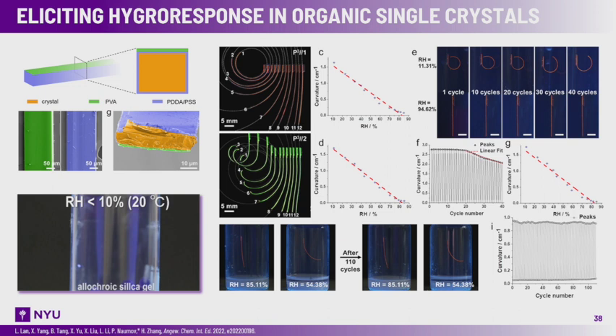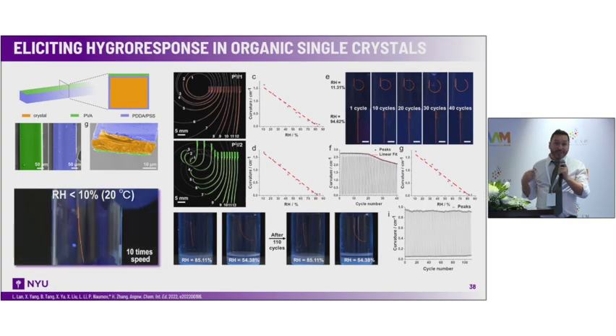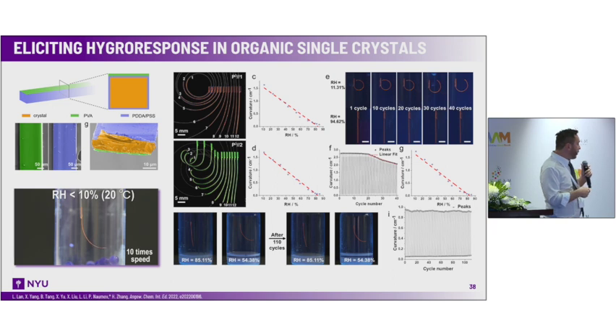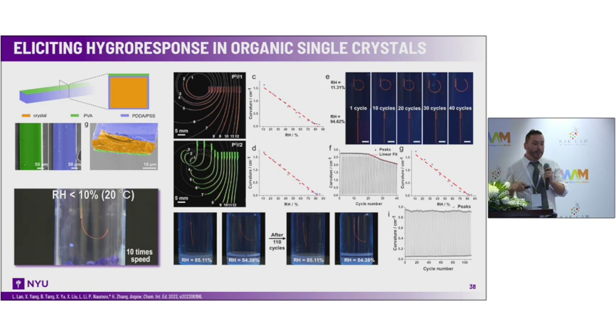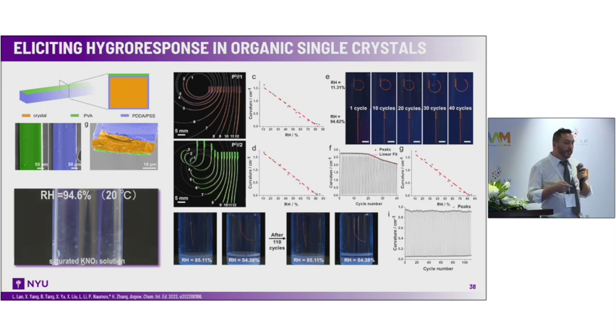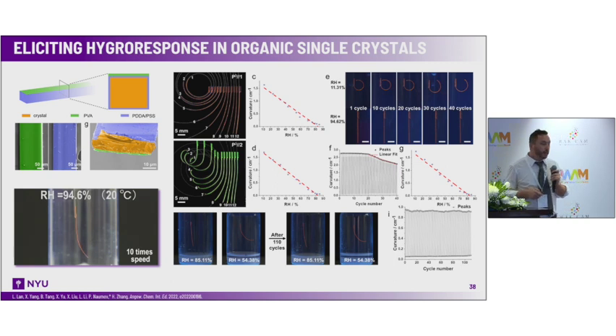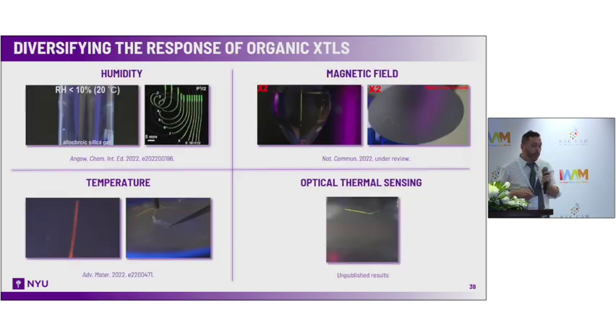Other things that you can do is change the stimulus. So I talked about light, I talked about heat. Recently we have been coating crystals with polymers that respond to humidity. In this particular case, we have an example where a crystal has been coated with a humidity-responsive polymer, and we see again deformation, and we also have a linear dependence on the level of the humidity, and that makes this crystal a kind of humidity sensor.